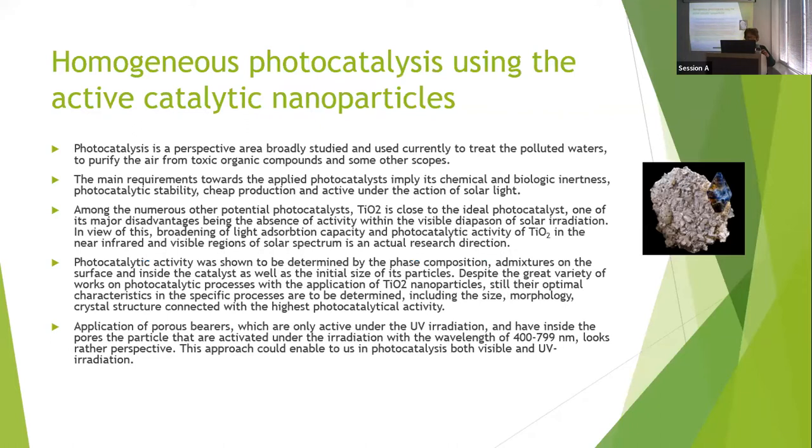Generally, this area is broadly studied already, and currently it is used to treat polluted waters, to purify the air from toxic organic compounds, and for some other purposes. The main requirements for the applied photocatalysts imply their chemical and biological inertness, photocatalytic stability, cheap production, and activity under the action of solar light. Among the numerous other potential photocatalysts, titanium dioxide is close to the ideal photocatalyst, one of its main disadvantages being the absence of activity within the visible spectrum of solar irradiation.